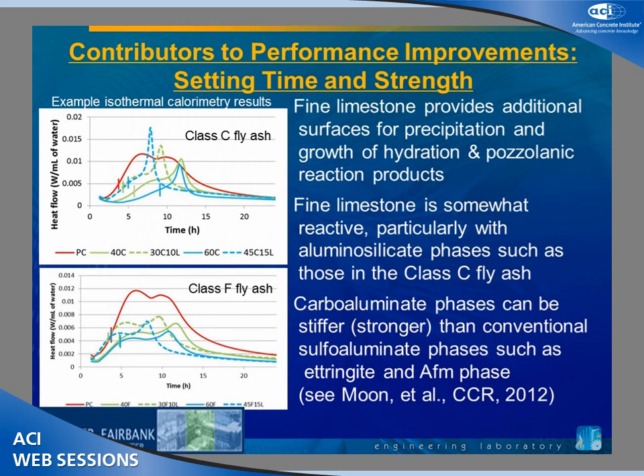We went back and did calorimetry work, and we can definitely see the acceleration that is provided by the limestone. The fine limestone, particularly the surface area, is important. It's providing additional surfaces for the precipitation and growth of reaction products. There are some indications that the CSH likes to precipitate on the limestone particles even more than it likes to precipitate on the tricalcium silicate and dicalcium silicate that are in the system to start.